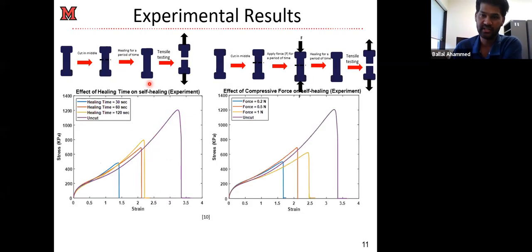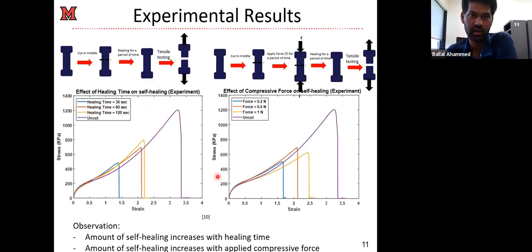Okay, so now let's look at some of our experimental results, what our colleagues found. When they perform the testing, two parameters are important. One is the healing time, how much time you allow for the system to heal itself. Another one is the application of the compressive force, the magnitude you apply. From this plot, this is the uncut case where your material is not being cut, the pristine material. In the other cases, this shows how much time we allow the material to heal itself. It is very intuitive that when you allow more time, like 30 seconds, then 60 seconds and 120 seconds, the material recovers better.